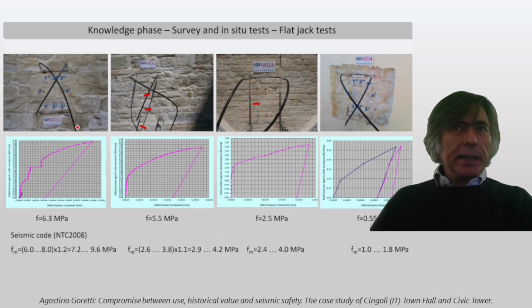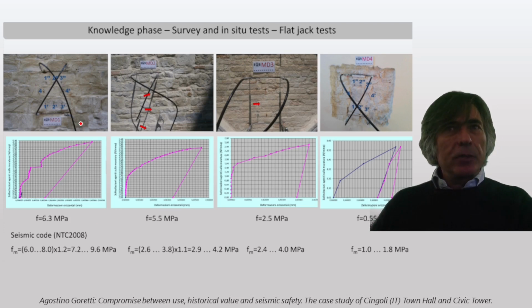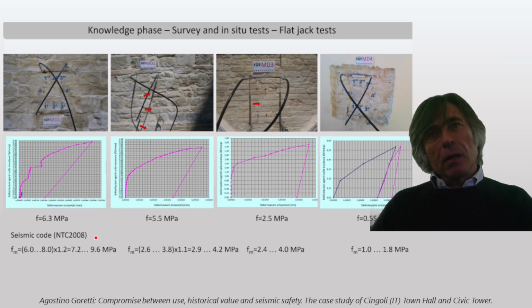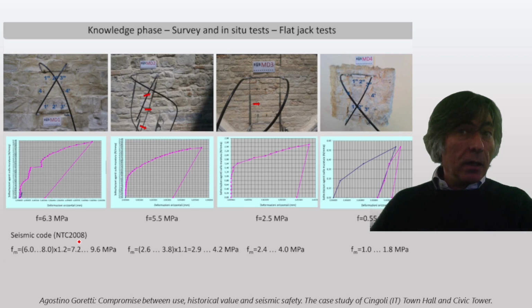Strength of the material. We performed a flat jack test on 4 different types of masonry, going from the well arranged and square masonry with thin bed joints, to a little bit more irregular layout with brick courses, the full brick masonry, and totally chaotic and irregular masonry. And we found several different, obviously, resistances, and I compared these resistances with what's suggested by the code.